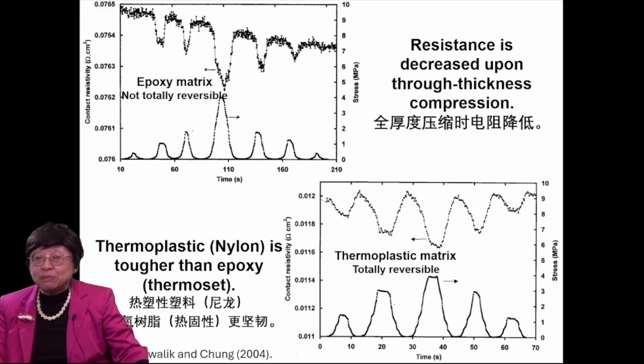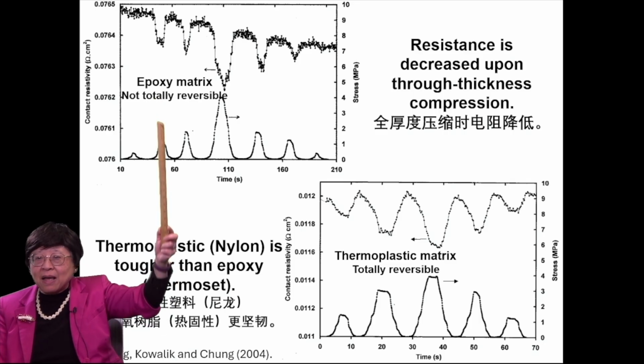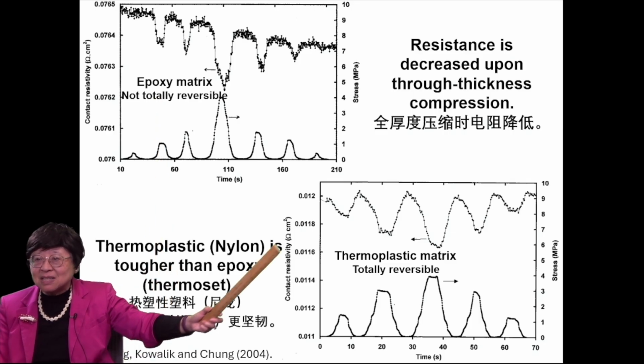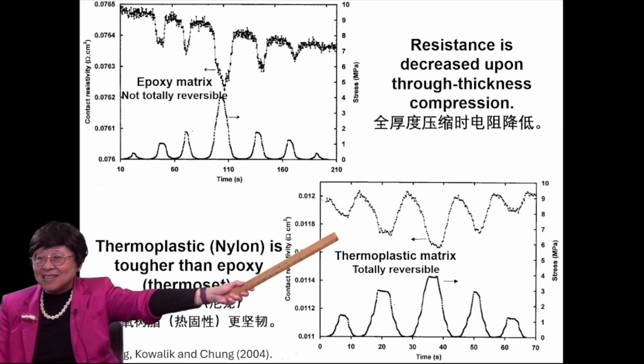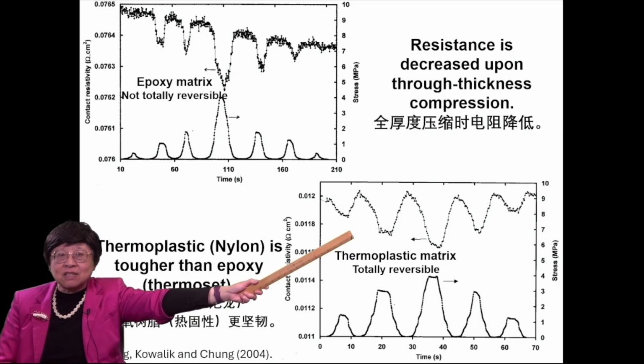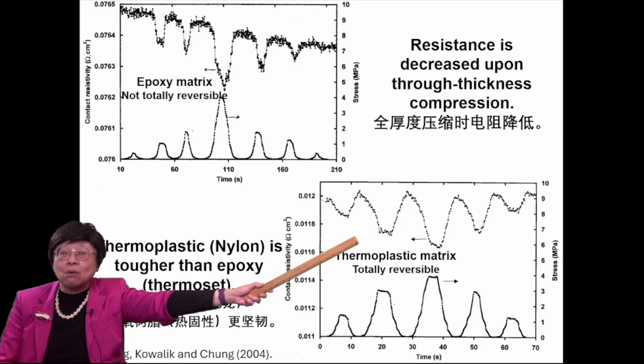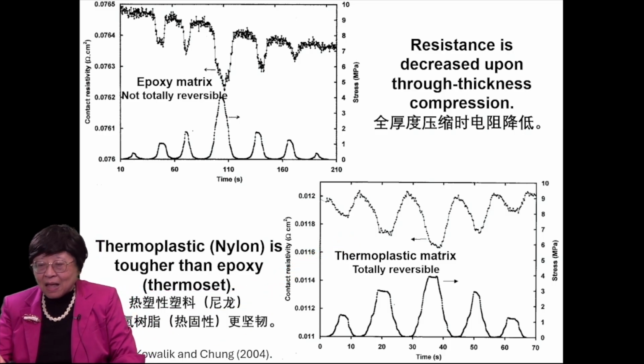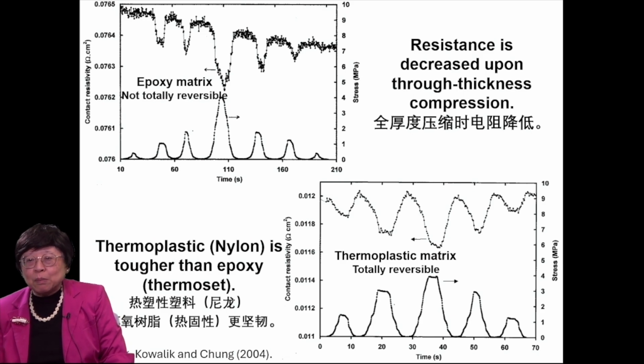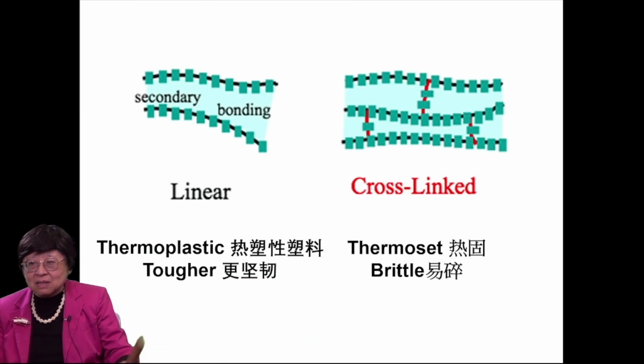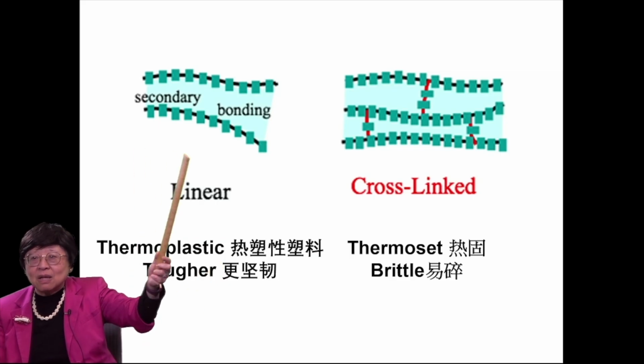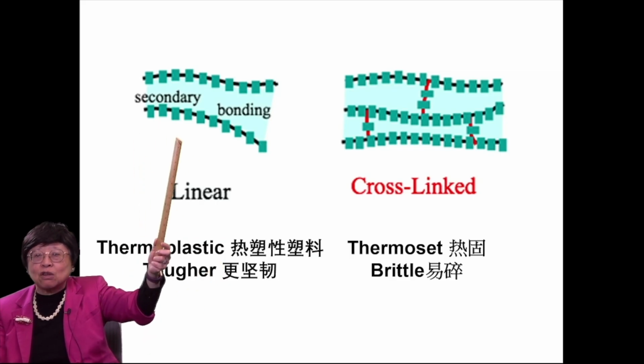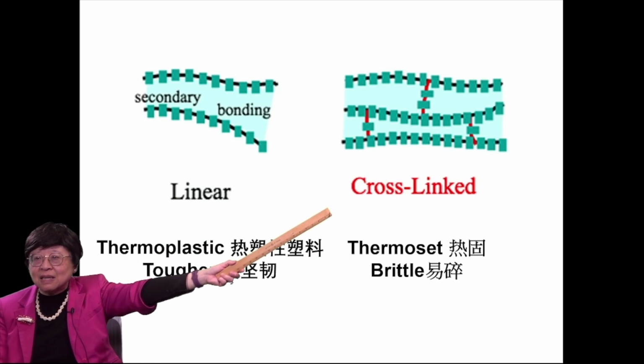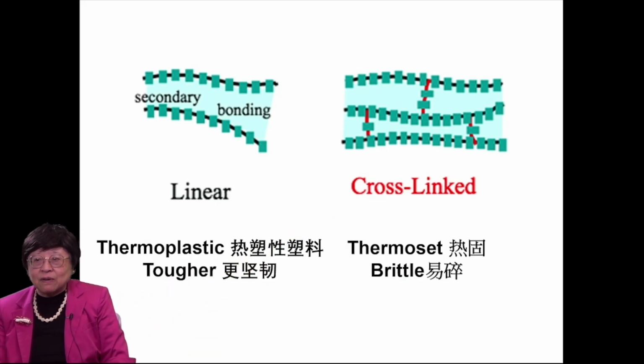However, if one replaces the epoxy matrix by a thermoplastic matrix, see, the contact resistivity decrease is totally reversible. And that is because the thermoplastic matrix is tougher than the epoxy matrix due to the linear chains in the thermoplastic and the cross-linked structure of the thermoset or epoxy. Okay.